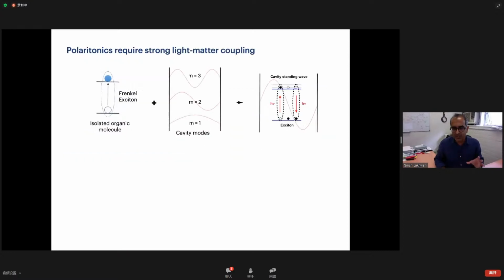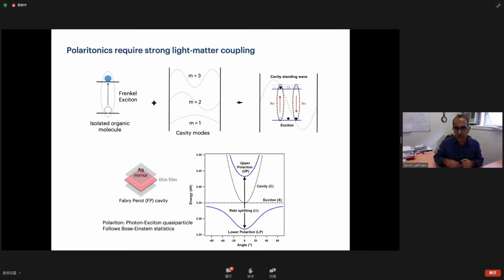And this is something which I get super excited about, because this is where I'm going to talk about optical cavities. If you take any material and put it in a cavity, which is nothing but two reflective mirrors, you can couple the molecule with the cavity. Once you reach a resonance condition where the standing wave inside the two mirrors matches the energy of your material, you will see that the energy levels split.